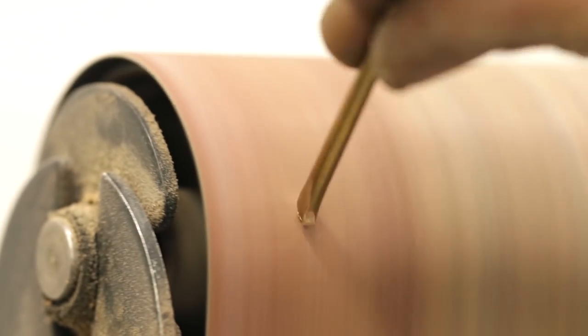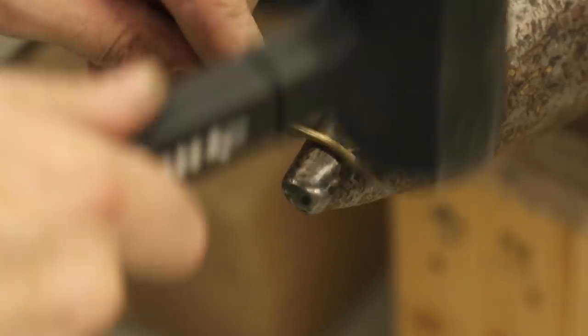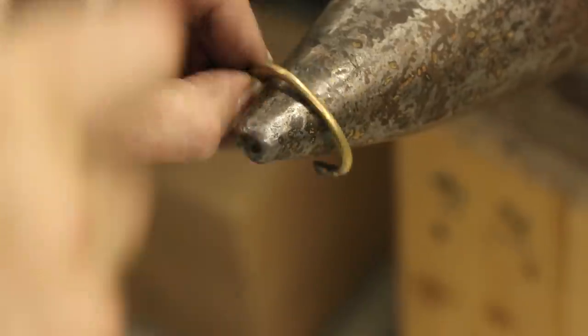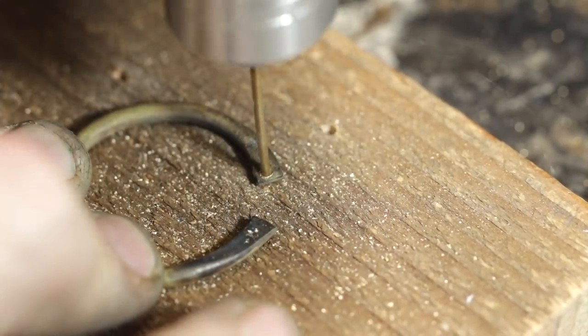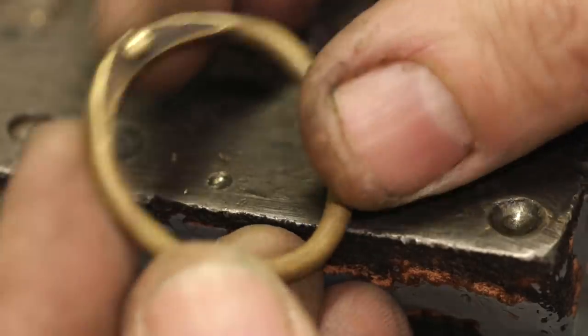Because I'm crazy, I decided I was going to make a custom ring for this. I've got O-rings all over the place, but I wanted to try making a ring because I'm on this metalwork kick. This isn't really my thing — I don't do this kind of stuff — so this is me winging it, making a ring out of a piece of round wire. I think I made three rings because I kept breaking them — I wasn't annealing them properly, I was hammering them too much, and they'd split. I finally got it down. Lots of good practice. That is the successful one, but I split them a bunch.